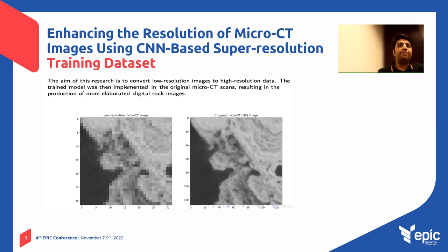As you can see in this slide, we have a cropped high resolution micro-CT image — exactly what we get from the micro-CT scanner — and this is the low resolution micro-CT image, obtained by downscaling using bicubic interpolation with a downscaling factor of 4. The low resolution image is 32 by 32 pixels and the high resolution one is 128 by 128 pixels.